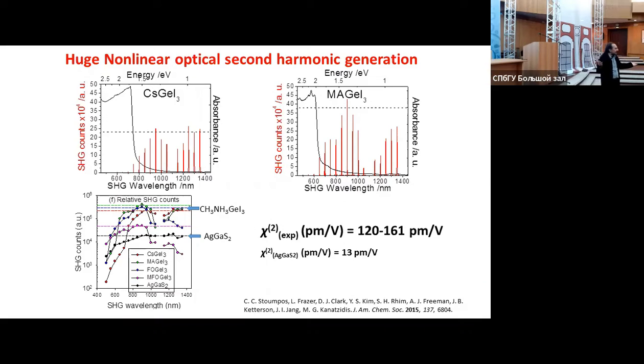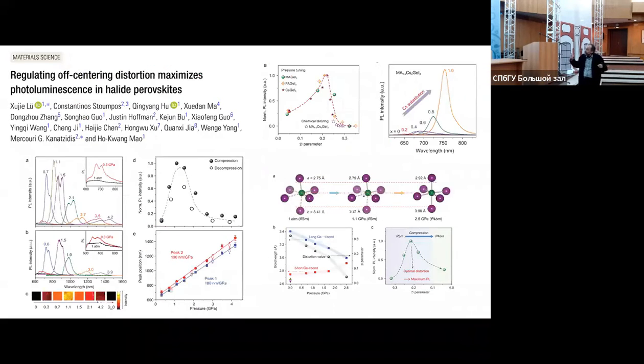Potentially, these materials could be ferroelectrics, never measured so far. But the reason is that they have quite large conductivity, and so the measurement itself is really difficult. But they also have another property, which we first found by doing high-pressure measurements in these materials. High-pressure measurements show a very large change in the energy gap as a function of pressure, as you see here. At various pressures, you see how the bandgap narrows significantly. And we realized that after some pressure thresholds, whereas you don't have very strong photoluminescence properties, basically zero,